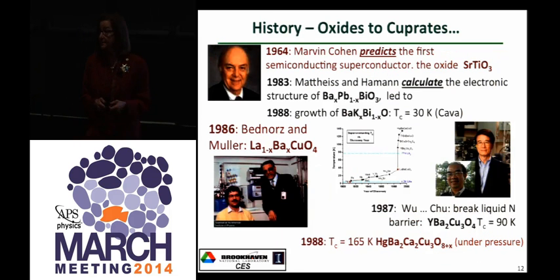Just to be honest, in the history, I need to talk about oxides, whether it's the prediction of strontium titanate becoming a superconductor. And then Mattheiss and Hamann calculated the electronic structure of barium lead bismuth oxide that led to the growth of barium potassium bismuth oxide. These were where theorists were actually helping a lot and maybe getting a handle on, can we design new superconductors? Whether they actually designed these or are serendipitous is still up for discussion, but these are a bunch of really smart guys that came up with new superconductors.